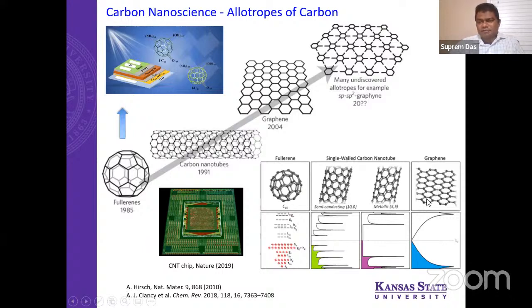Now, if you look at graphene, it's completely different. The band structure is completely different. It's linear, or you can say conical, at the Fermi level. It's very, very linear. And this is the first time that people saw this linear band structure. That is the beauty, that is the speciality, and that's the single most reason why graphene is so different from other materials. But having almost 17, 18 years of discovery, it's not just graphene.